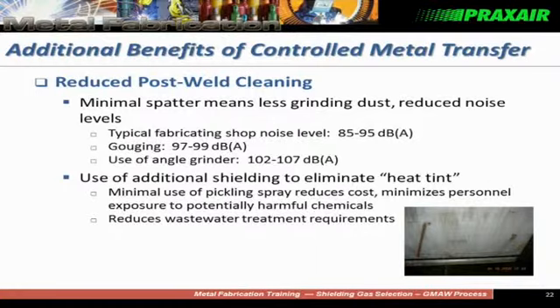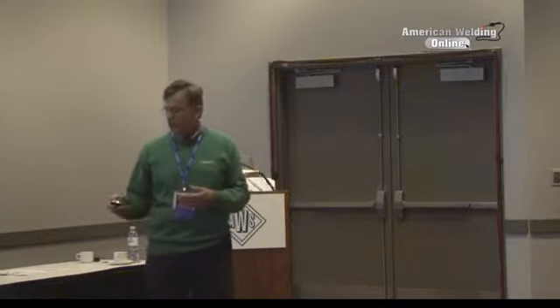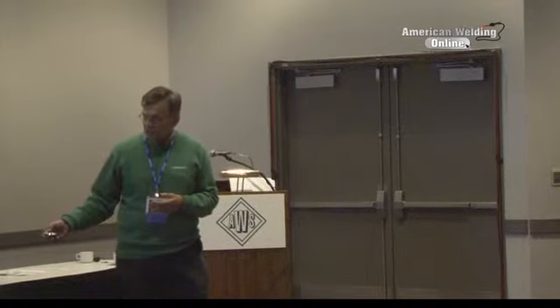One of the other things that we had run into, I had worked with a customer on a welding related problem. This is actually the back side of a stainless steel dump truck, one of these large trucks that you see with stainless steel containers in the back. But they're welding stiffeners, or pieces of material, to stiffen the surface of the large truck containers. But from welding these stiffeners on, the outside, or the side that you would see, say, from the street, discolors. And so this is what it would look like.